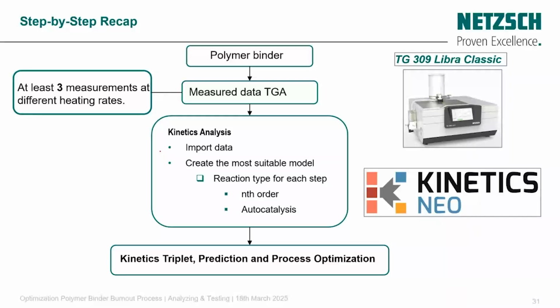So, a step-by-step recap. In order to optimize the process, we need a polymer binder, then we do the measurement by TGA, at least 3 measurements at different heating rates. If the R square is more than 0.995, in this case it's perfect. Otherwise, we need to do more heating rates in order to increase the accuracy of the model. After that, we do the kinetics analysis. So basically, we import the data and create the most suitable model with the different reaction types, which can be n-th order, autocatalysis, first order, second order, and so on. Then we can go to the different outputs or results, the kinetics triplet or the different kinetics parameters like the coefficient of determination, the prediction, and also the process optimization. And therefore, the industries that we have experience with, after that they are going to do the validation of the process.